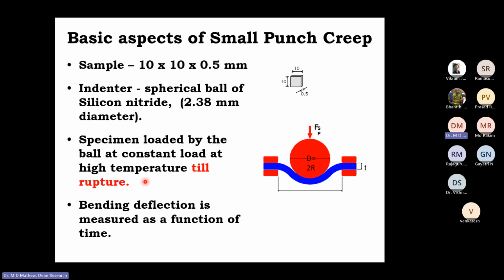So some of the basic aspects of the small punch creep is, yes, the sample size is very small. Then what is the indenter here? The indenter is a silicon nitride spherical ball, around 2 to 3 millimeter in diameter. And you load the 10 by 10 by 0.5 mm square specimen using this indenter. So the spherical ball is loaded, the ball is touching the sample. Once the ball is loaded, the specimen undergoes creep deformation. The specimen is loaded by the ball at a constant load. And of course it is creep, so temperature is high. And the test continues till the sample breaks, the material ruptures.